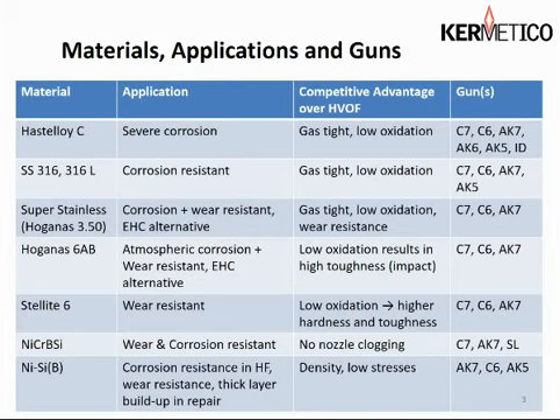Stellite 6, pretty popular coating at the refineries, a wear-resistant hard stuff. We spray with low oxidation, and we achieve higher hardness and better ductility or toughness than the HVOF or plasma versions of the coating. And once again, we haven't found a reason to spray that with our smaller guns.